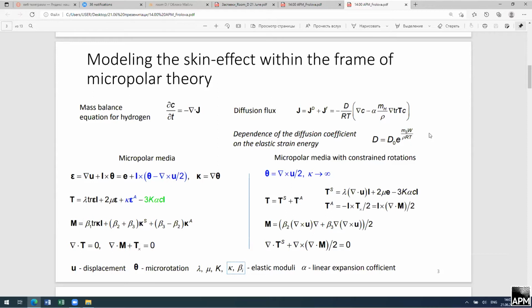Here we want to obtain a subboundary layer with a stress strain state that differs significantly from the bulk material. And here we use micropolar theory of elasticity since it has been already applied a lot of times for a number of problems with size effects. A particle in micropolar media can be considered as an infinitesimal solid body with independent rotational and translational degrees of freedom. Therefore, stretch tensor and wryness tensor are introduced, and constitutive equations are written for stress tensor and couple stress tensors. Here we assume that hydrogen can lead to aging strains and use Duhamel-Neumann constitutive equations for the stress tensor. And we solve two balance equations.